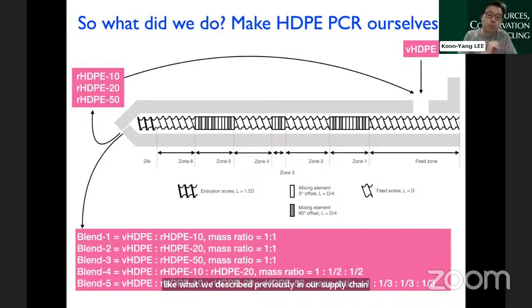So on those formulations, we call them blends. So blend 1 is a virgin HDPE with high density polyethylene that are passed through the extruder 10 times. Blend 2 is virgin HDPE with recycled HDPE that are passed through the extruder 20 times. Blend 3, remember this keyword, blend 3 here, is virgin HDPE mixed with recycled high density polyethylene that are passed through 50 times. Now, these serve as our second benchmark materials, all right? Blend 1, 2, 3. 10, 20, 50 times recycled polyethylene mixed with virgin polyethylene.